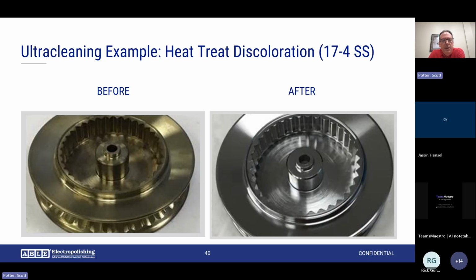These parts are unusual in the fact there's a number of different steps that we actually perform for the customer. It's a ratchet system that's used by people that are doing rescues, firemen, and window cleaners. But it's a critical part. They sent us the parts. We degrease the parts. Then we send them out for heat treat. Then we send the parts out for the opposite face to be blasted. And then we do the final electropolishing, which you can see on the right side there.